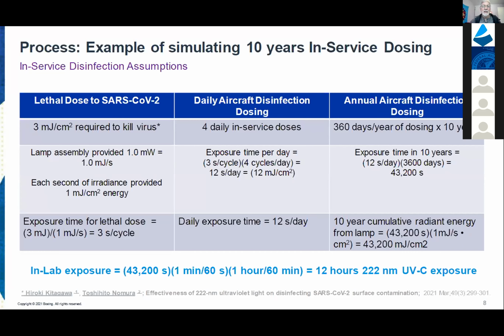The other assumption we make is, how many times would the airlines do this a day? We thought what was reasonable was, let's just assume it's 4 times a day and 360 days a year, and basically let's assume it's over 10 years. So for each day, 3 millijoules for every time you apply a UV dose that's lethal. 4 times a day means 12 millijoules per square centimeter per day times 3,600 days, equaling 10 years. And you see that number in the bottom there, 43,200 seconds.